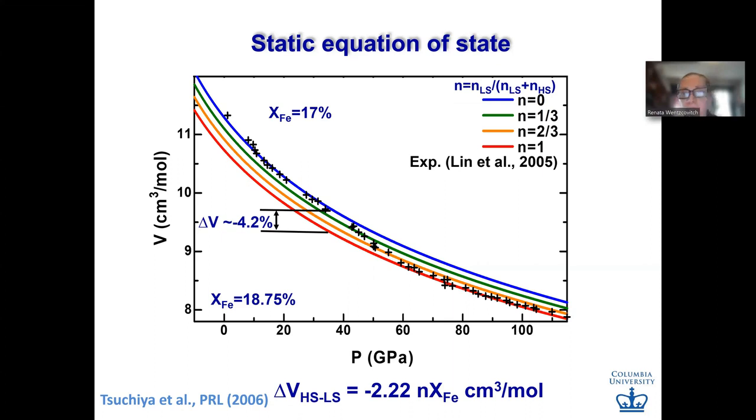And these are the slides that led me to this conclusion. Here you can see the compression curve for the same supercell with 1/3 of irons in the low spin state or 2/3 of iron in the low spin state. So that's essentially the physics. Between high spin and low spin, there is a mixed spin region where these configurations are coexisting.